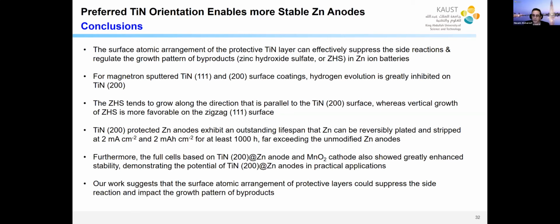But to grow it on the 111 direction, because the atoms are not flat, if you recall, I showed you, actually the energy is negative. So the energetics of growing this second undesired phase on the 111 tin nitride is actually favorable. So it's easier for it to grow. And that is the root cause of this thing.